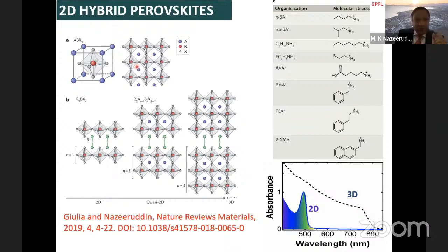Now, what happens if your cation size is bigger than the cavity? For example, we are using cesium as an inorganic cation or methylammonium as an organic cation. So this cation easily fits into this cavity to form a three-dimensional perovskite material. Now, tomorrow you change the cation from methylammonium to phenylammonium, phenylethylammonium, as shown here. And this cation size is so big, this will not fit into the cavity, so that the layers are split into low-dimensional perovskites. So now you have a great opportunity to tune the dimensionality by combining the smaller cation